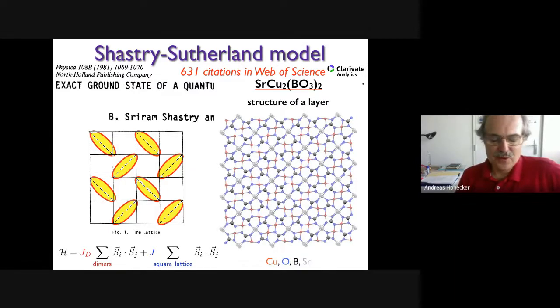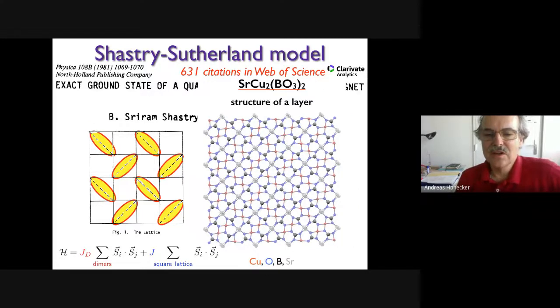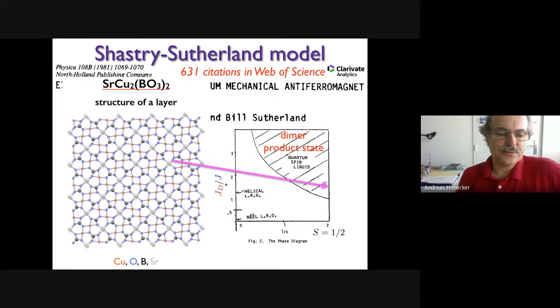And since copper is in the 2+ oxidation state, you have a spin 1/2 system. And so basically what strontium copper borate is doing, it is realizing that exact dimer product state, but it's pretty close to the transition to the Néel state. So it is on the right of this plot and close to the transition.